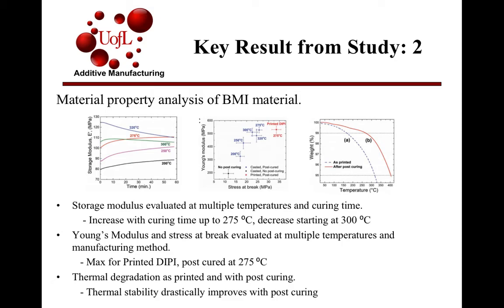Lastly, the researchers looked at the thermal degradation, comparing printed and then printed with post-curing. You can see here on the right, the blue line is just printed, the red line is printed with post-curing, and it's obvious here that thermal stability dramatically improves with the post-curing process.